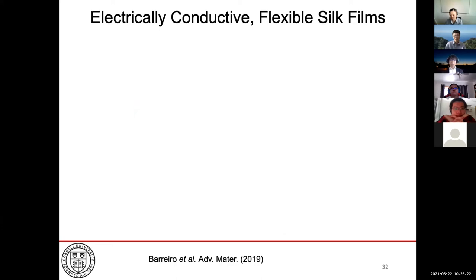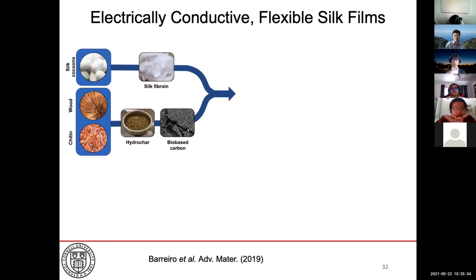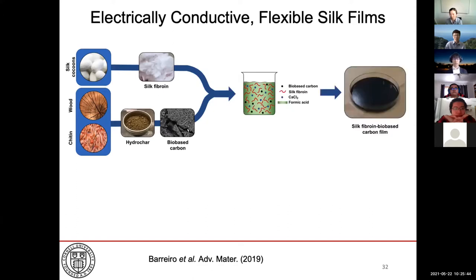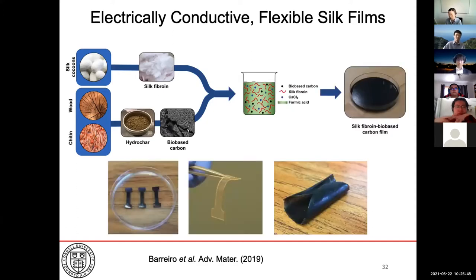And we took this concept further by incorporating sustainable materials from nature to obtain electrically conductive flexible silk films. We added wood or chitin that were processed under high temperatures and pressures to obtain activated aromatic carbons that were electrically conductive. And by dissolving these components and casting them into films, we obtained thin and flexible silk films that were electrically conductive.